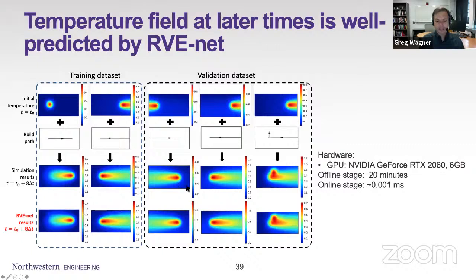But these validation tests are showing that this middle row here is what we treat as our ground truth, right? This is the simulation of the heat equation. Our fast evaluation is giving a temperature field that matches that simulation result well, but it's doing it in a very small fraction of the time, right? In this case, a thousandth of a millisecond for some of these, and we can achieve that through parallelization, right? So we're solving multiple instances on GPUs in this case.